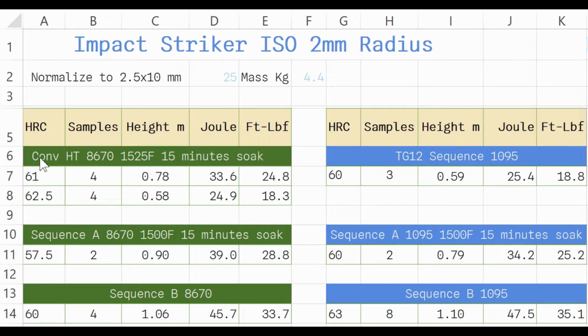For the reference, which is the conventional heat treat of 8670, I retested it because in the previous video the head of the striker was 1 millimeter radius. So the head actually has a very narrow force focus, and digs into the sample and initiates a shorter crack line, a lot of compression, and then creates tension on the opposite side, so it breaks a little sooner.